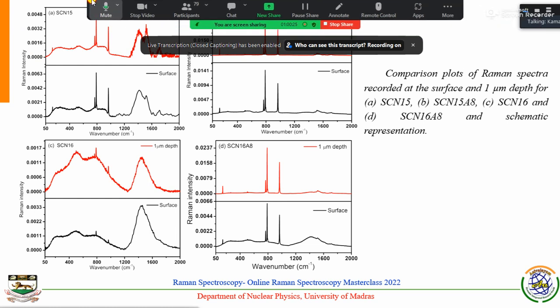See, from the surface, if I approach 1 micrometer, the intensity of the peaks decreases, but instead the amorphous peaks also increase. You can identify that, so the Raman intensity decreases at 1 micrometer. And similarly, after annealing, we can observe that at 1 micrometer the intensity of the crystalline peaks is increased up to 4 times. Okay, you can see, but at the surface it's very much lesser.